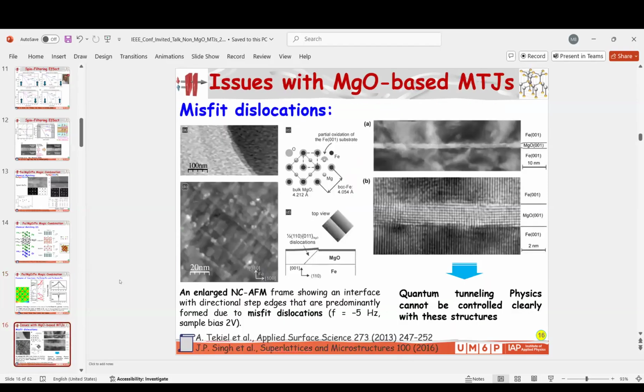So what about the issues with MgO? I will go through them a little bit fast. We have the misfit dislocations. In this paper, we did an extensive study about the surface, and we have here some cracks, let's say cracks, dislocations. From the top, you see it like this. From a cross section, we have here misfit dislocation, which will diminish, for example, PMA, perpendicular magnetic anisotropy, and it will make the control of RA, resistance area, a little bit difficult.